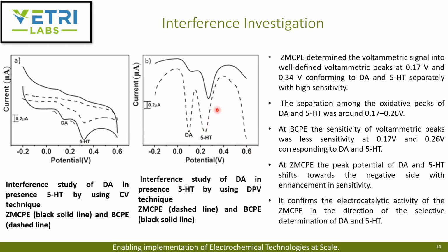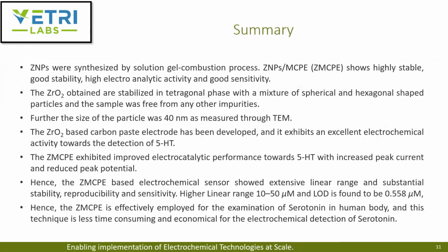So in summary, they used a gel combustion process to produce zirconia oxide nanoparticles, which had a good sensitivity and a good stability. The zirconia oxide nanoparticles were in a tetragonal phase with a mixture of spherical and hexagonal shaped particles, about 40 nanometers in size. The developed carbon-based electrode had high detection towards 5-HT, with an increased peak current and reduced peak potential. They had a linear range of 10 to 50 micromolar with a detection limit of about 0.558 micromolar.